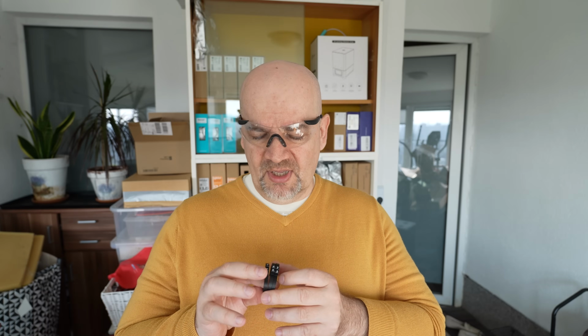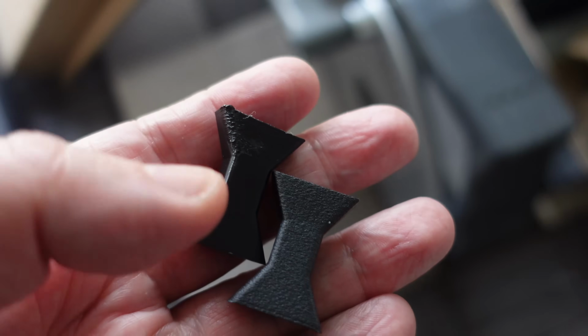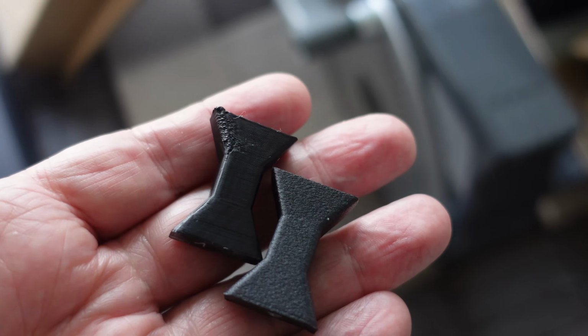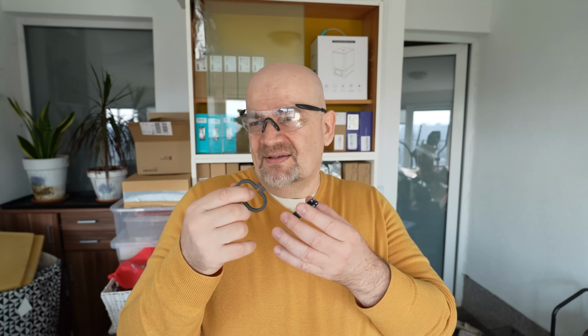Quick conclusions for the end. PPA is a great material with fantastic mechanical properties. I don't really like the non-reinforced versions. The printability is not so good, and probably I should even lower the print temperature or increase the part cooling, but in that case, for example, the layer adhesion would be weaker too.